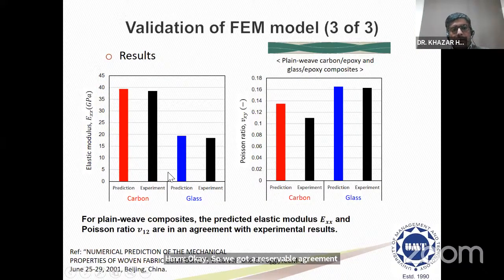Okay, so we got a reasonable agreement when we compared the experiment versus the simulation result. That means our finite element model is giving reasonably accurate results.